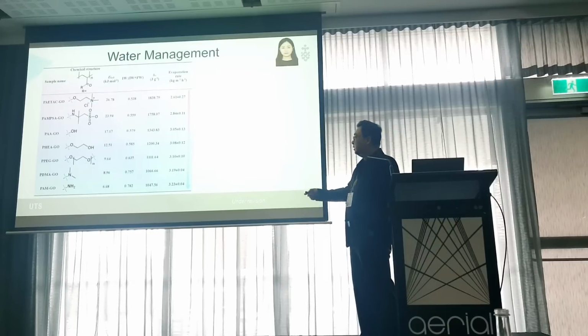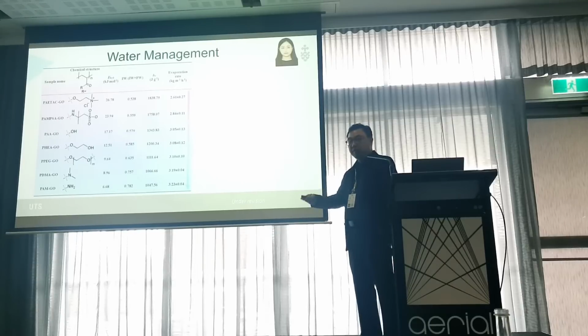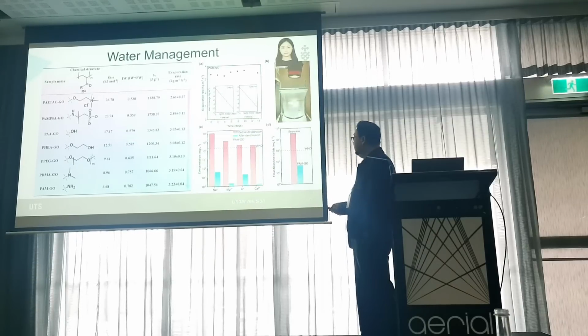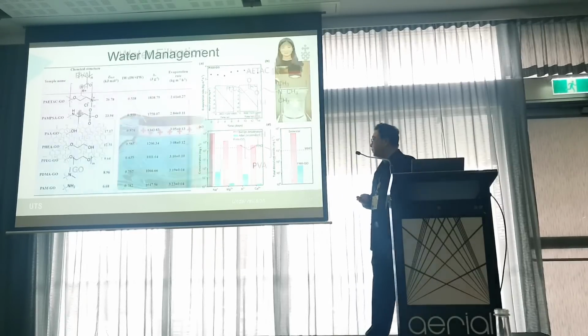So we tested the evaporation performance as expected. This hydrogel showed the highest water evaporation because it had a high content of intermediate water. Then we did a second test with seawater, and we observed that the salt concentration is very low compared to distilled water.